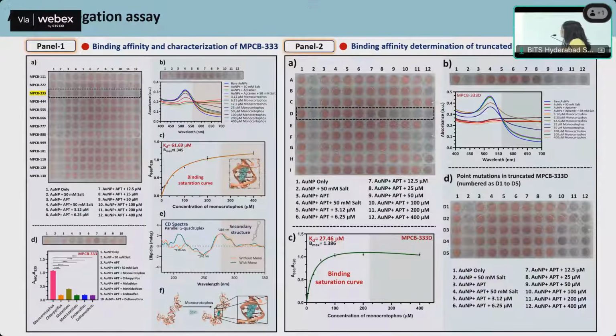After gel and cloning, we found 13 unique sequences, and aggregation analysis gave us the clue that the MPCB333 aptamer was very promising out of all sequences. This is the UV spectra of the same aptamer. The KD value was around 61 micromolar. Again, it was not so good. CD spectra showed that it is forming G-quadruplexes, and we also did docking. The cross-reactivity analysis was done with several pesticides, and it was specific for monocrotophos.